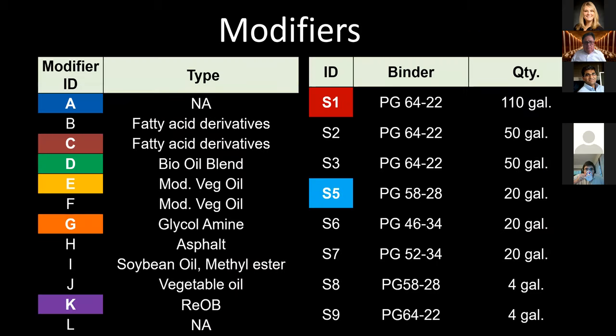As you can see by this slide, we had a very ambitious experimental plan. There were 12 modifiers and 8 binders that made up the initial matrix. S4 binder was removed from this study because it did not conform to a PG 58-28. Binder S8 is a binder that was used in a field test section by IDOT and was modified with modifier L. As you can see on the slide, we also give the generic chemical makeup of it. We have kept this study blind to product names. We're just looking at the generic chemistry and trying to evaluate them on basic classes of materials.